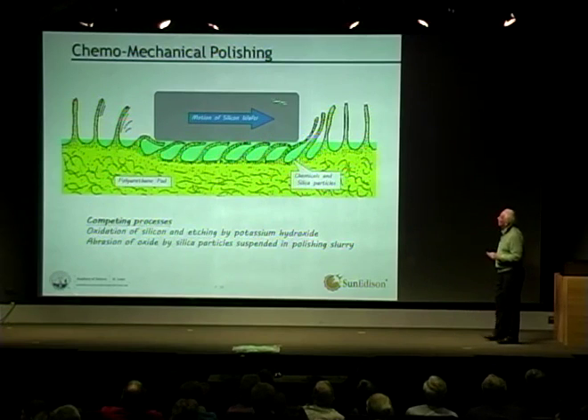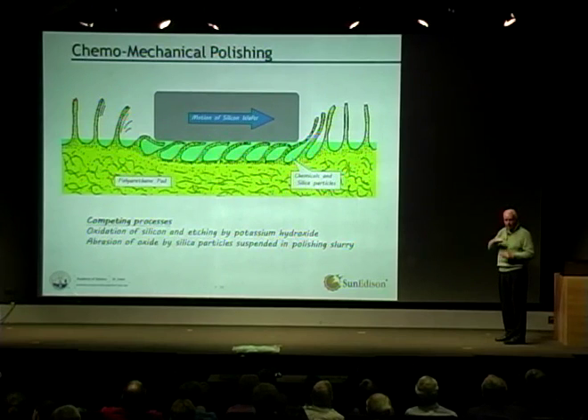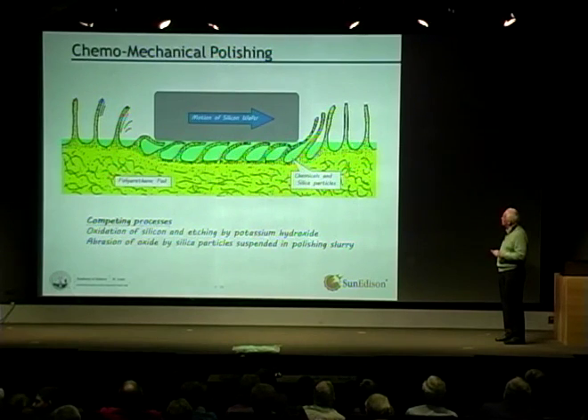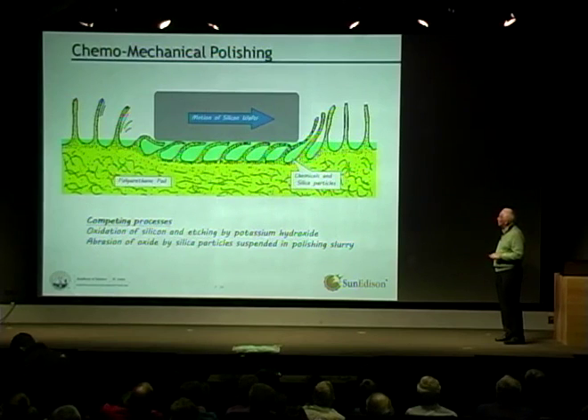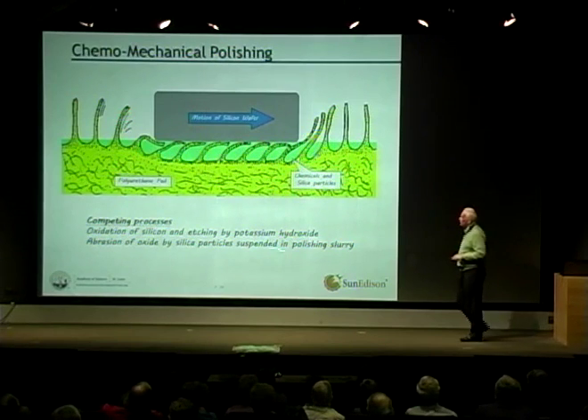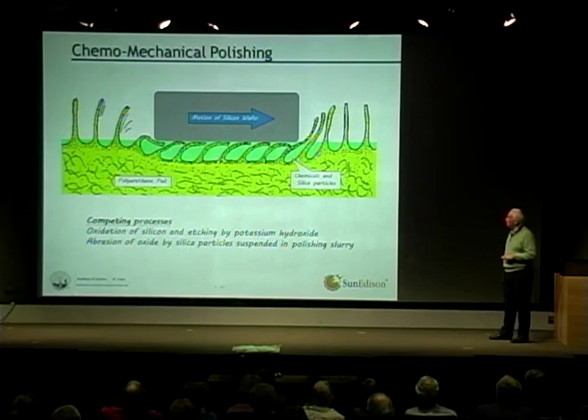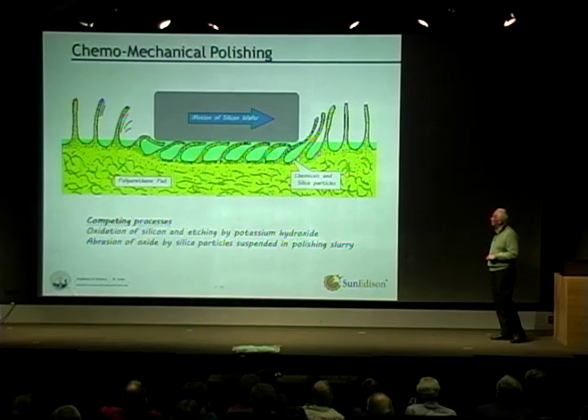What's going on? Here's a silicon wafer. It's moving across the nap of the pad. When you actually look at the pad, it's not quite like a brush as it's shown here. The nap is very short. These bristles are extremely short. But under a microscope, it looks something like this. You drag the wafer across. Here's the slurry represented by the green. And it's held in between the nap and in the pores. And you drag the wafer across with these chemicals. And the chemical involves a suspension of silicon dioxide particles in potassium hydroxide.